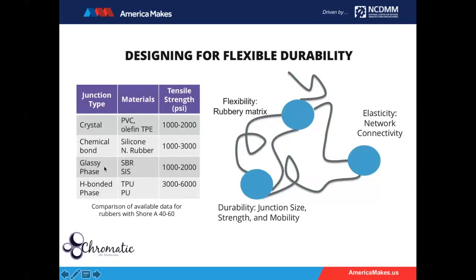If you have a glassy phase, like styrene butadiene rubber or styrene isoprene, these blue dots are made up of a glassy material like styrene, and there the tensile strength is 1,000 to 2,000. But a polyurethane or TPU can stand out because in those cases the junction points are hydrogen bonded, and that brings a large degree of strength to the junctions. So you get a bump above the other classes of materials in tensile strength: 3,000 to 6,000 psi. So that's generally how one goes about designing a flexible, durable material. To get durability, you look at how strong and durable you can make these junction points.